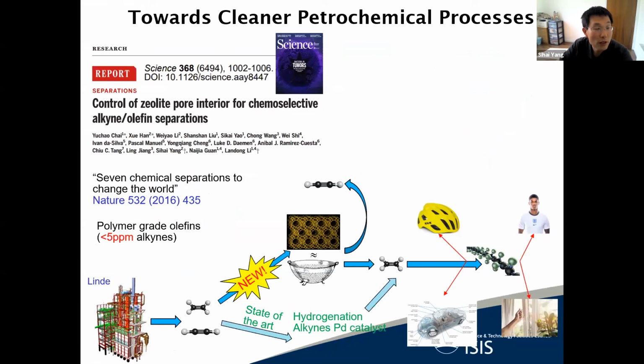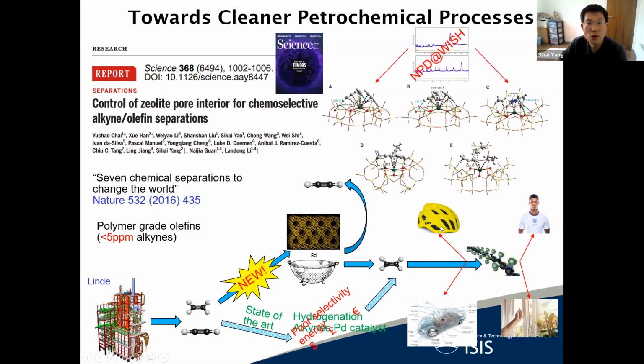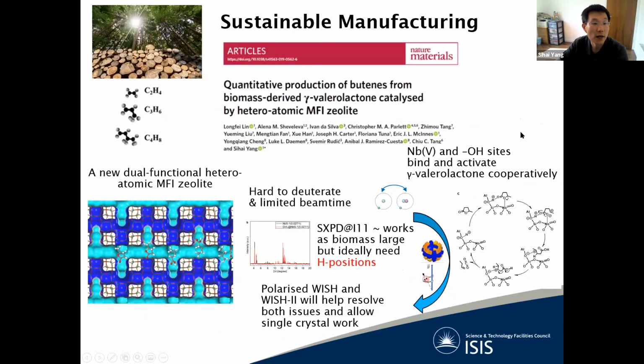And another recent example is on the study of separation and purification of lower olefins, which clearly is very important in terms of manufacture of many materials we use today, from homeware to cars. The traditional way of purification is via hydrogenation over noble metal catalyst, which is clearly energy intensive and has a poor selectivity. So what we have done here is develop a new zeolite material that can do molecular sieving to remove the impurities, and therefore give pure lower olefins. And this is the WISH study we have done to visualize the binding mechanism between the acetylene on the top and the ethylene in this case, to reveal the difference in their nature.